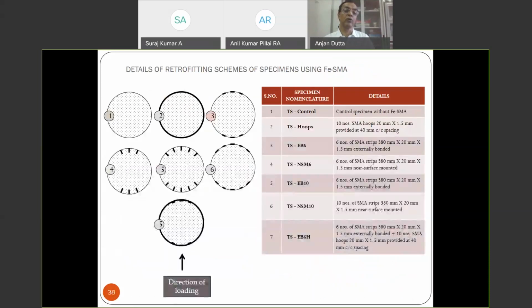Now this rehabilitated specimen, different strategies we'll try to use now. One specimen will be your control specimen, one will be only using hoop reinforcement, one will use what we call near surface mounting. We'll only mount strips on the surface. And then if we use thermal activation, because we are using reversible loading, we have seen the loading protocol to simulate the dynamic environment. So it will generate the tension phase on this side as well as on this side. And we are using near surface mounting. After thermal activation, it will introduce tension in this zone, compression in this zone, so that whenever you have tension because of loading, it will try to nullify those tensions.